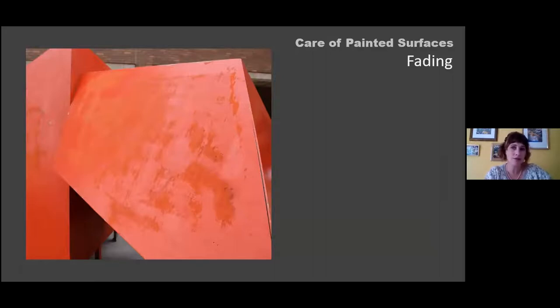Fading depends on the type of paint — some paints are much more stable than others — and on light levels. In a gallery display with oil paintings and natural light, they may be durable enough, but you wouldn't lock them in direct sunlight. In this case, an outdoor painted sculpture that had been repainted on several campaigns shows how the top layer of paint began to fade, discolor, and take on an almost chalky appearance, also abrading away to reveal a distinctly different color below.